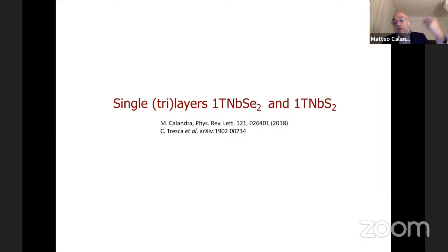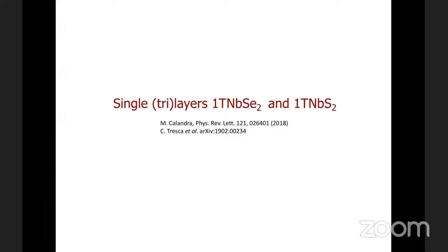And not only do you have it in the electronic band structure, but you also have it in the force constants. The force constants are derivatives of the total energy that includes the electron-electron interaction. Okay, but what you're telling me is very similar to, say, BCS theory that leads to a superconductor. So what actually changes here? I mean, at a harmonic level, right?